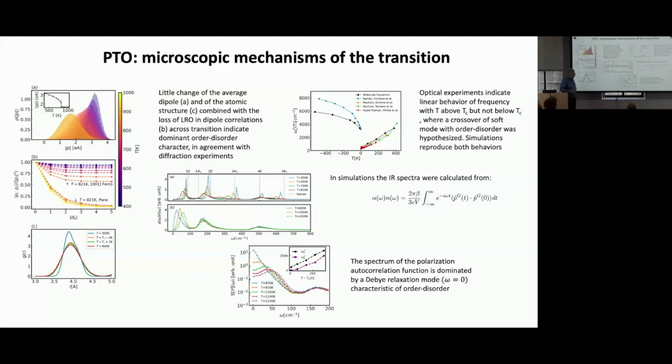I think that the same thing should happen in Raman, because in Raman, typically, when you go to frequency close to 0, there is the Rayleigh scattering mode that masks the effect of the Raman. And so typically what happens close to omega going to 0 is taken out by something that plays a similar role to the omega squared here. So we can understand this kind of detail based on those simulations.